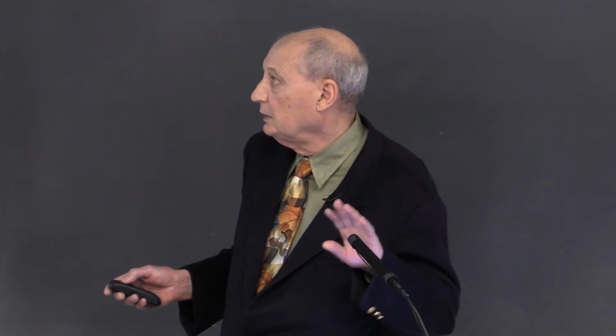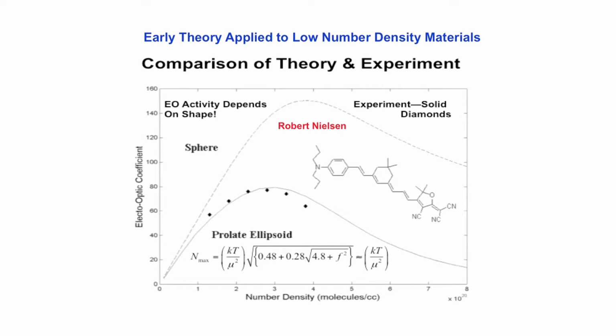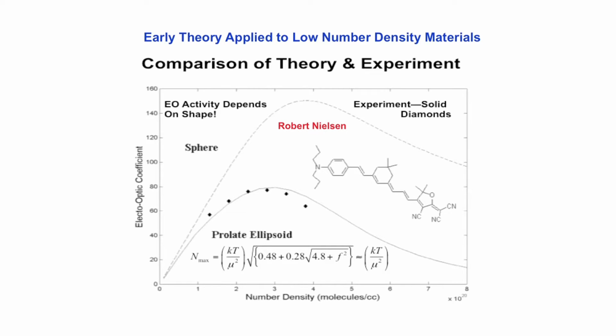Now, I'd like to break our theoretical consideration into two time periods. The first deals with theory applied to low number density materials. So this is taking a chromophore like this and dissolving it in a common polymer like polymethyl methacrylate. And initially, everyone assumed that these would behave as independent particles and that the electro-optic activity would increase in a linear manner with number density because the acentric order parameter was independent of number density. Well, as you see experimentally, this is what everybody saw.